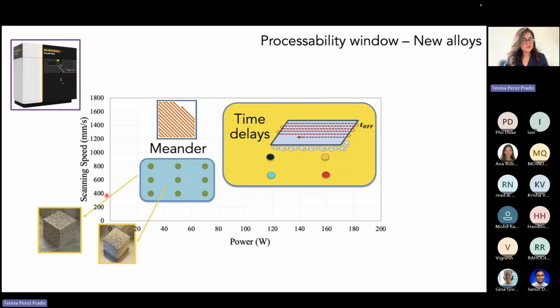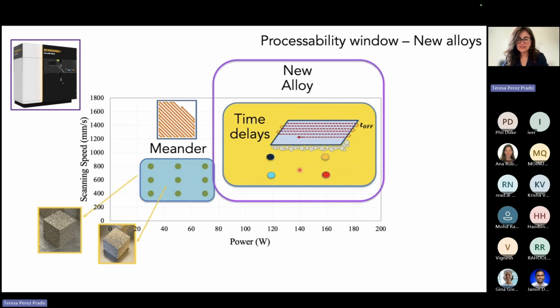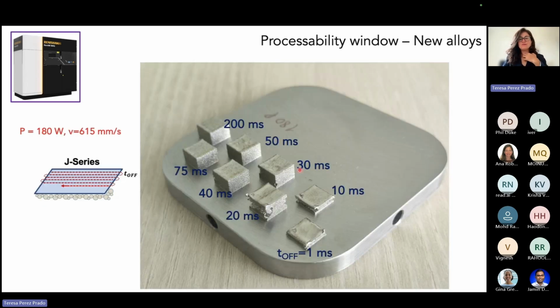So again, I come back to this processability window that you know very well. This was where we could print only using a simple scanning strategy, but we want to print these new alloys within this orange domain, because this is where we can get higher densities and better properties. The first question for me was, if these alloys are so great, now they have such a much larger glass formability, can we print them without time delays? And this is the first thing that we tried, and this is what I'm showing you here.